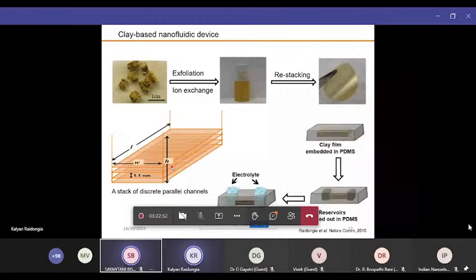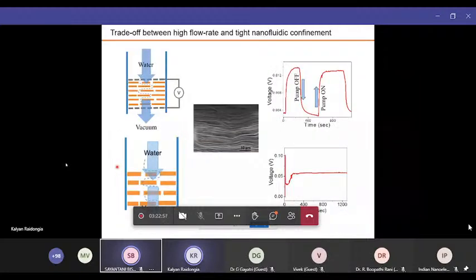But then when we made a device and tried to push water through it, we definitely got some voltage, which is very small, like 12 or 13 or 15 millivolt range. But this is good for the proof of concept, but not for realistic application. The reason the voltage was very small is that the channels are so small. When it is 1 to 2 nanometer range, it is very difficult to push liquid through it. It is extremely difficult.